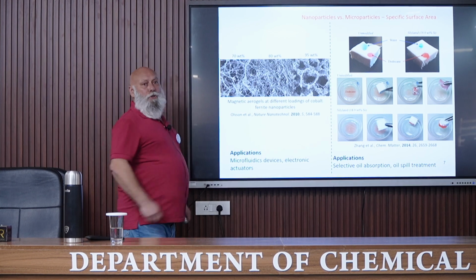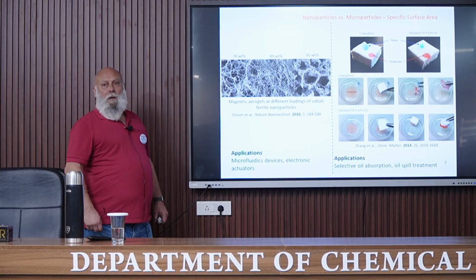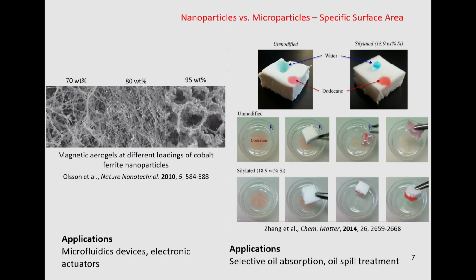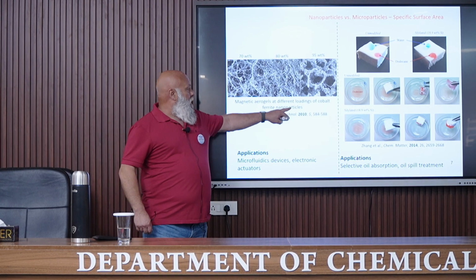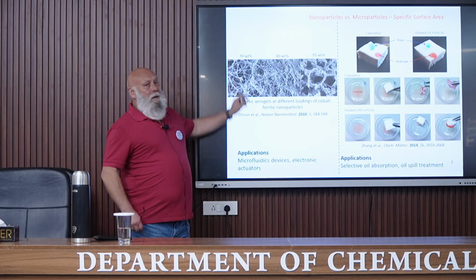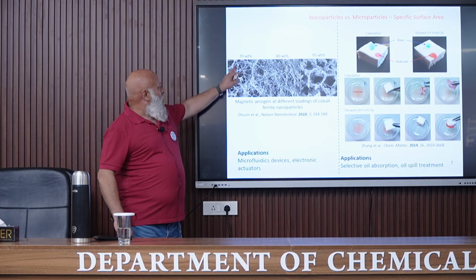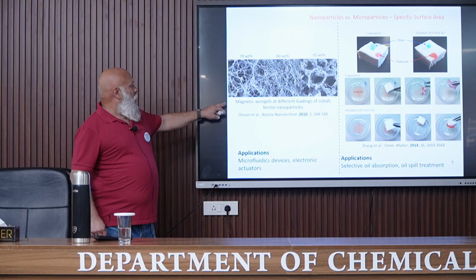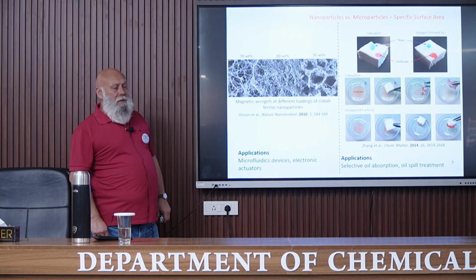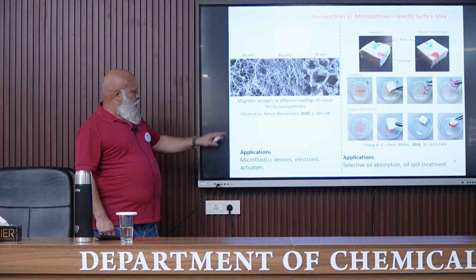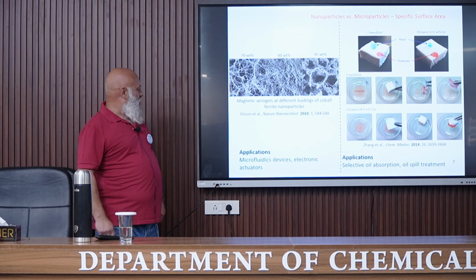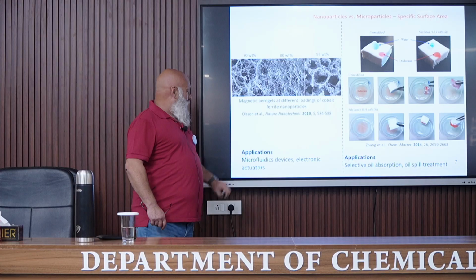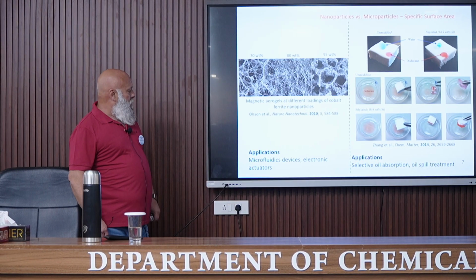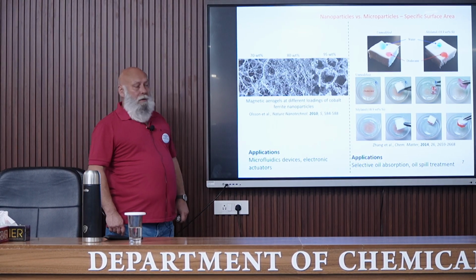This cryogel can be functionalized. So it means that a chemical modification can be performed, we'll see this on the right, or we can attach different particles. For example, in this case, cobalt ferrite nanoparticles have been attached to the surface of the nanofibrils, at a different percentage, leading to an aerogel with magnetic properties. We'll have another example in the other slide with different particles that can be attached, but the possible applications are for microfluidic devices and electronic actuators.